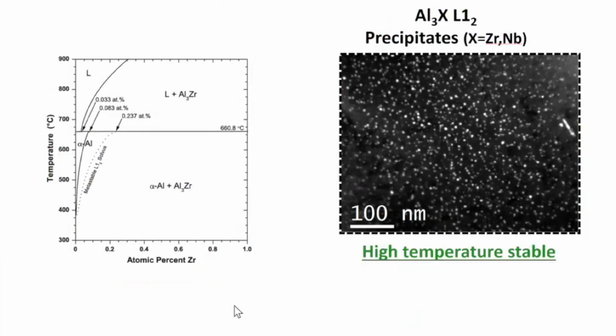Unfortunately, however, you cannot have a large volume fraction, as you can see from this diagram. It is the same thing with zirconium, where a small amount of niobium is added to stop the cellular precipitation so that you get a homogeneous L12 precipitate. The volume fraction is low because of the phase diagram. Even if you take the metastable L12 solvus, it is very near to the pure aluminum side, and therefore you cannot have a large volume fraction of the precipitate. And if you do not get a large volume fraction of precipitate, you cannot increase the strength. Though it is high temperature stable, coherent and everything, it really cannot be used as the only precipitate to strengthen the aluminum alloys. So what can I do?